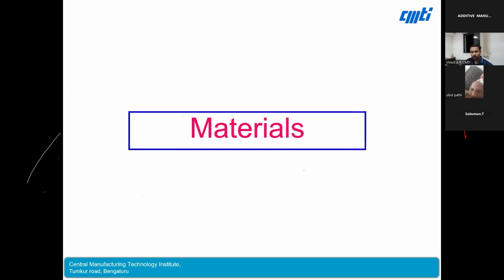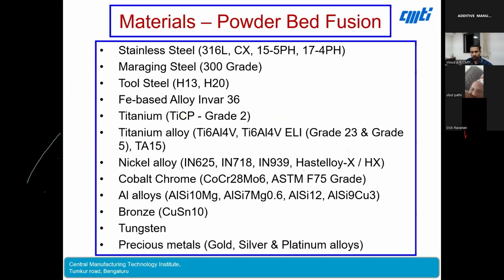If you look at the material options, there are many material options available in powder bed fusion technologies. Different types of stainless steels are available, like 316L. We have 15-5 PH and 17-4 PH, and maraging steels, especially for tooling applications. Then you have titanium alloys, pure titanium also, and Ti-64 alloys for aerospace, and medical grades are available. Inconel superalloys are there, like Inconel 625, 718, Hastelloy, cobalt chrome, aluminum alloys. Like that, you have different materials.